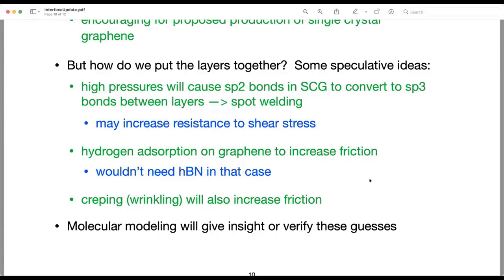The other way is, perhaps we don't need hexagonal boron nitride. Perhaps we can stay with the single crystal graphene, but adsorb hydrogen on the graphene. This option would increase the friction, and then we could stick with one material. Another thing we could do is sort of wrinkle or crepe the material in some of the layers, and that would also increase friction. But we've identified a major sub-study, I guess you could say, within the study of molecular modeling. So we're really going to need to verify that we can even do the spot welding or to understand the hydrogen adsorption and things like that. We need to do molecular modeling, and we're in the process now of identifying software that can do that.